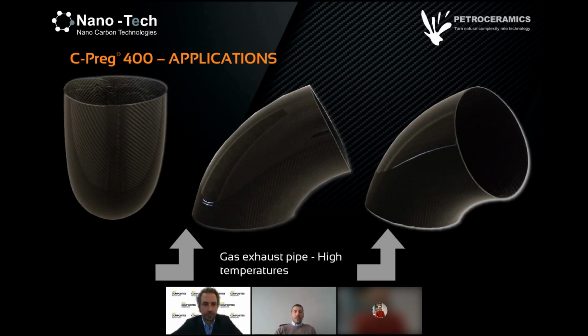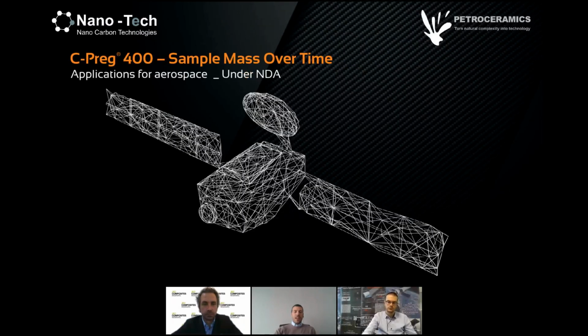We have an example of a gas exhaust pipe for high temperature made with Cpreg 400. This is quite a big object, let's say, that was obtained by curing in autoclave and then post-curing in oven. And we even did a paint test of the composite with good results.